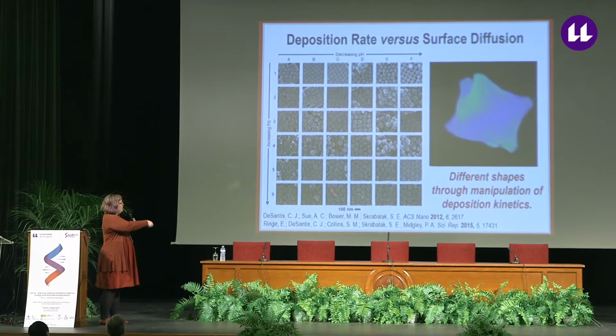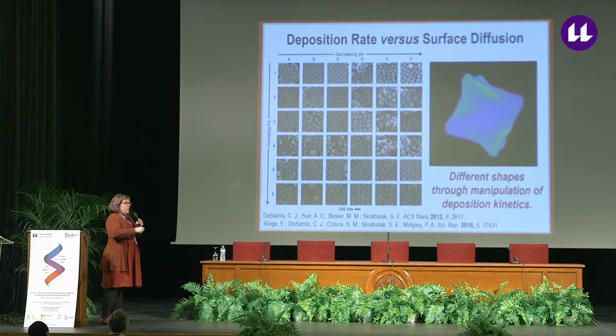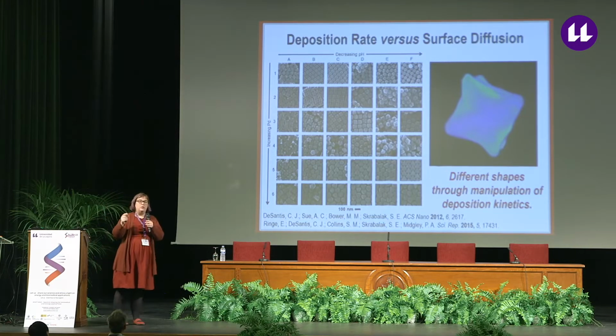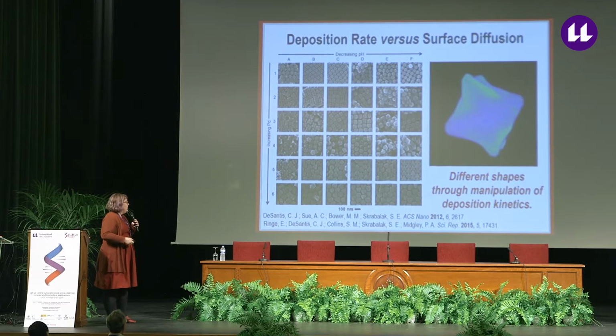In addition to the octahedral-shaped nanoparticles, we have cubooctahedra, nanocubes, and then 8-branched octopodal nanocrystals, where there are 4 branches out from the board towards you, 4 branches back into the board. Or if you looked at the tomogram here of a single nanocrystal, you could see that there are indeed 8 branches. Each branch is proceeding along a 1-1-1 direction.